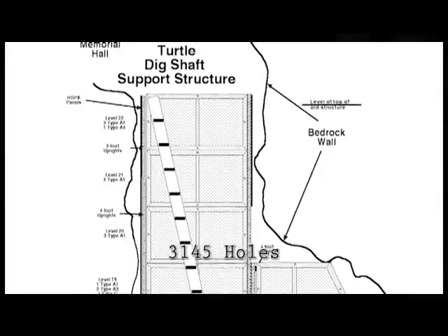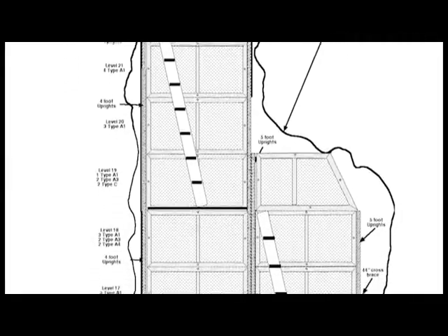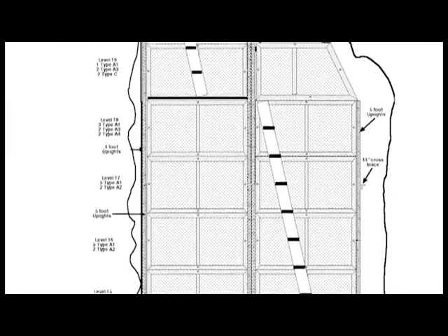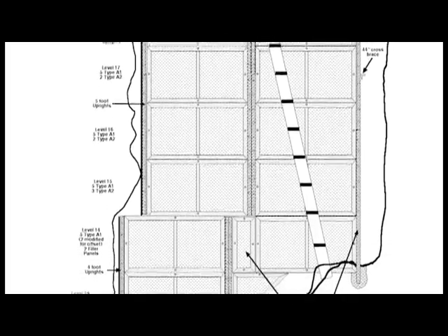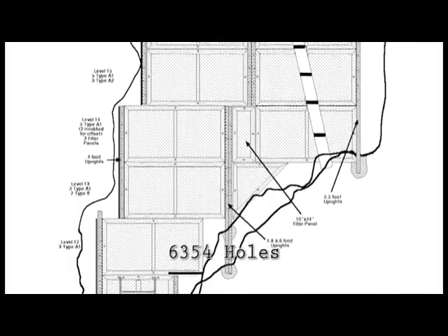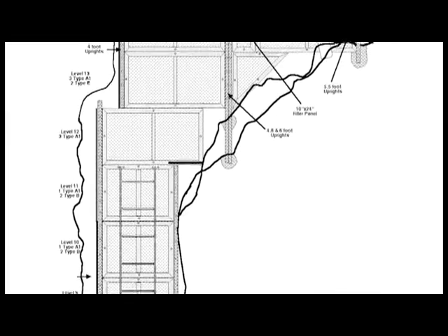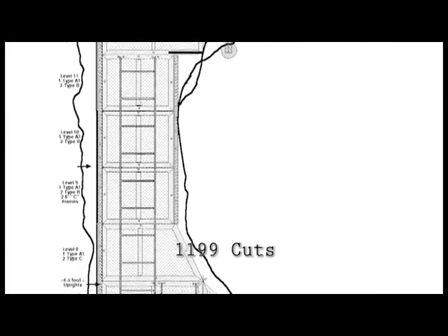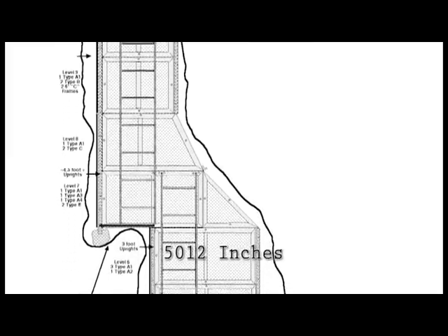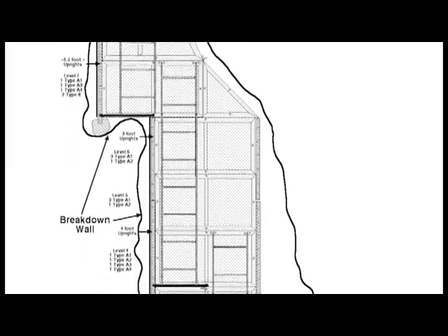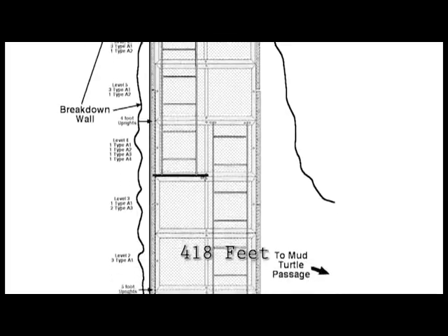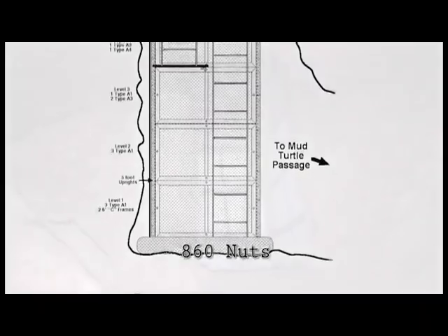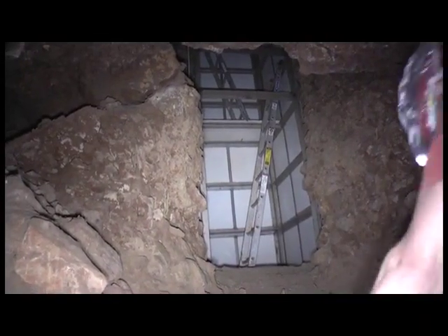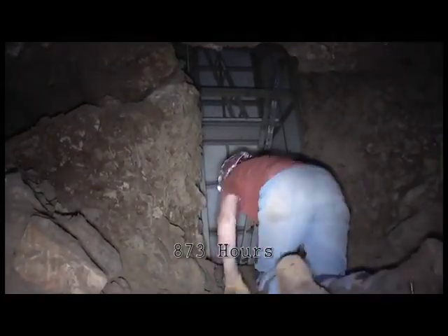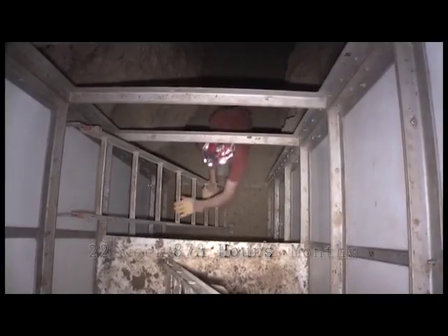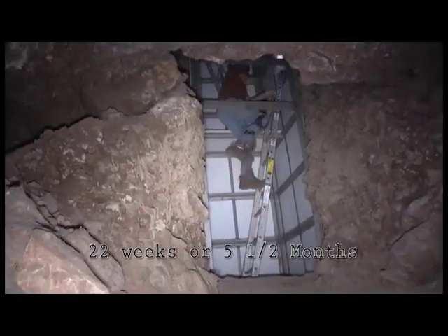To recap, 3,145 holes were drilled, and considering the fact that each completed hole was pilot drilled first, which means each hole was drilled twice, a total of 6,354 holes were drilled in the stainless steel. 1,199 cuts were performed, and 5,012 inches of weld was laid down, which is equivalent to a bead 418 feet long. 860 nuts were welded to the structure. The total labor time for fabricating the stainless steel was 873 hours. If based on a 40-hour work week, that's 22 weeks, or 5.5 months.